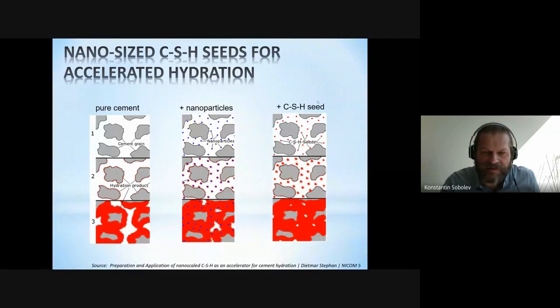And this is possible with CSH seed. So if you have a CSH seed incorporated, obviously you can have a better structure than you would have just with nanoparticles. Nanoparticles participate in the reaction, but CSH seeds are really the products which can have better acceleration and better structure filling properties, and can act also as what I call super glue, and even work with less reactive particles of supplementary cementitious materials.